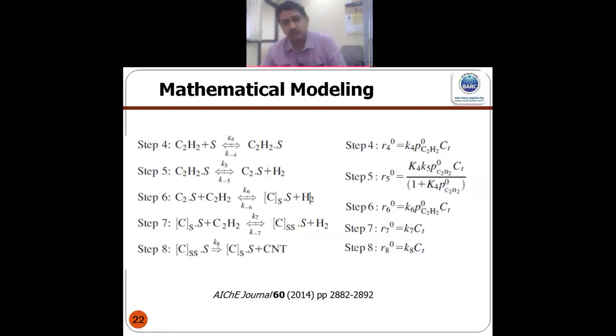So this is the model which we proposed, and for all these steps you can see these are reversible except the last step. And related to each step, if we consider each of them individually rate controlling, then we end up with the equation which is listed on the right hand side. Why I showed this?